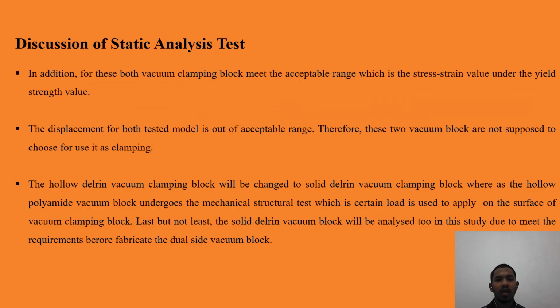Discussion of static analysis test. In addition, both vacuum clamping blocks meet the acceptable range within the stress strain value under the yield strength value. The displacement for both is out of the acceptable range. Therefore, these two vacuum blocks are not supposed to be chosen for use as clamping.